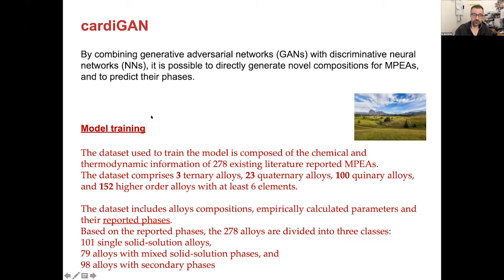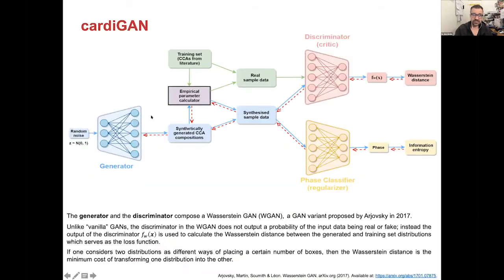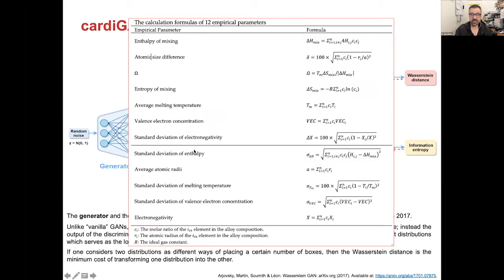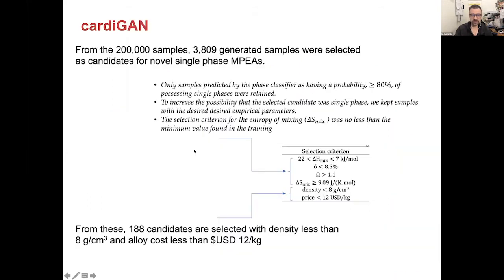So for those that have heard of GANs before, what we did in this particular case is we generated synthetic alloys and used a critic or a discriminator to discriminate those synthetic alloys so that we could generate a very, very, very large data set that was moderated by the empirical rules for alloy design and what was learned from the smaller database of actual data. These are the empirical parameters and their calculation.